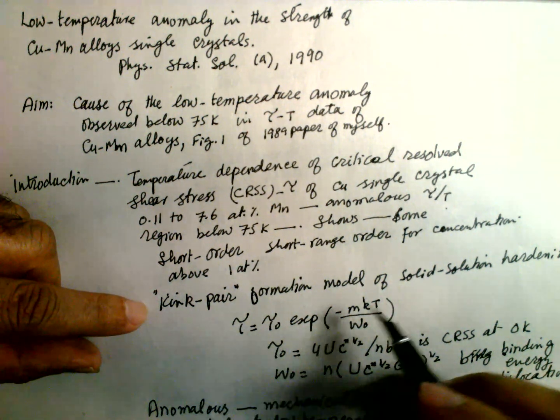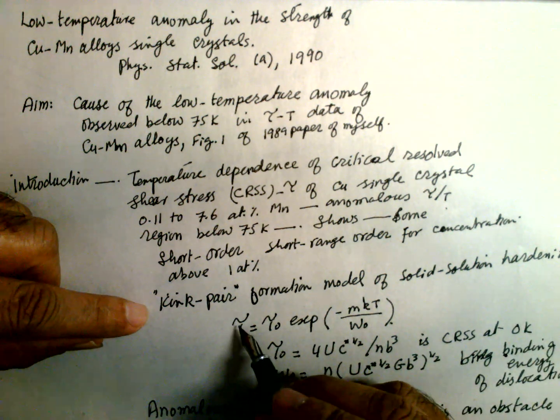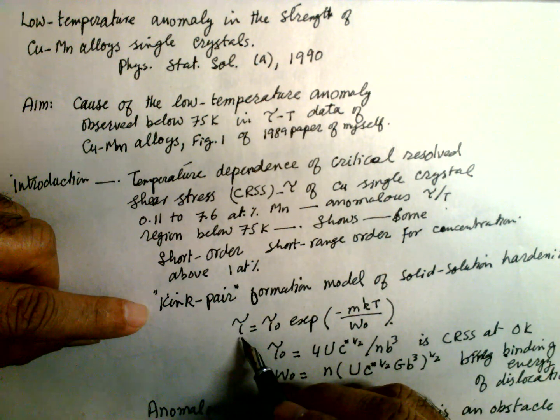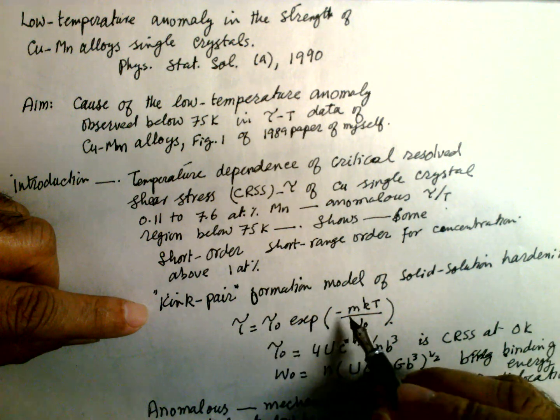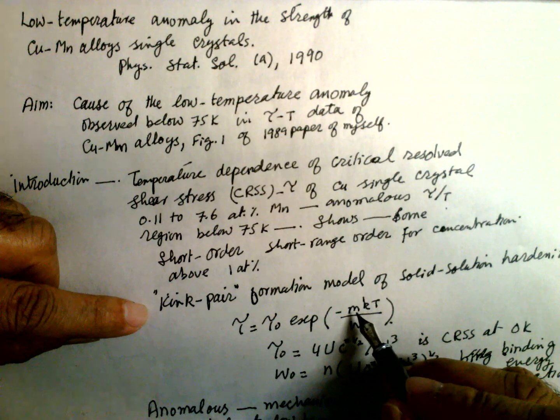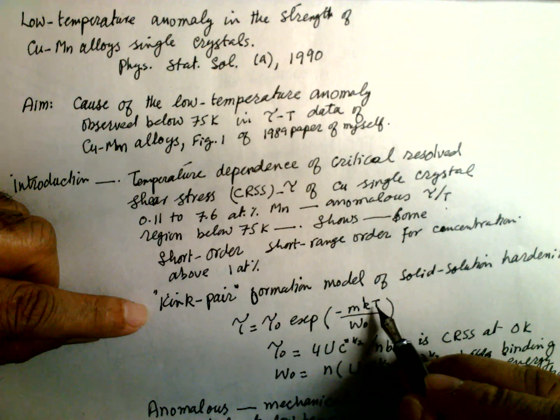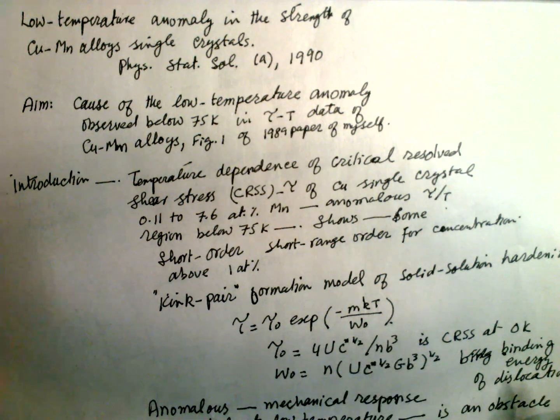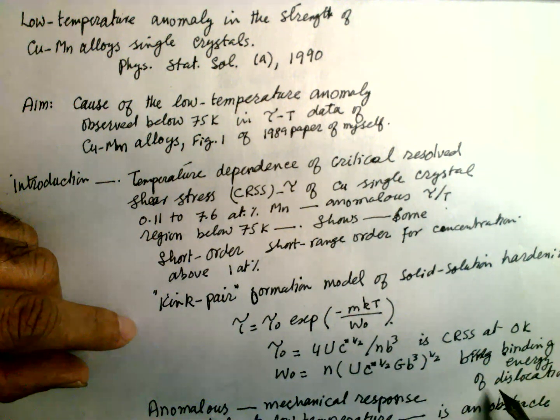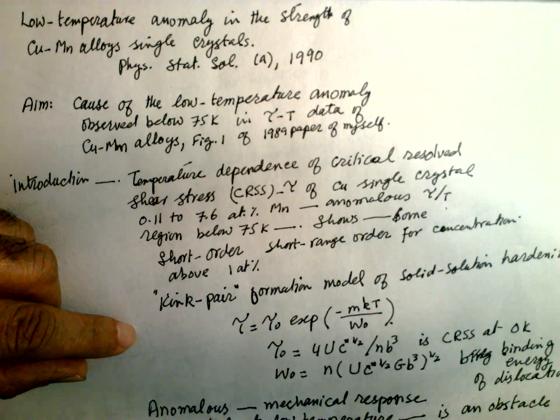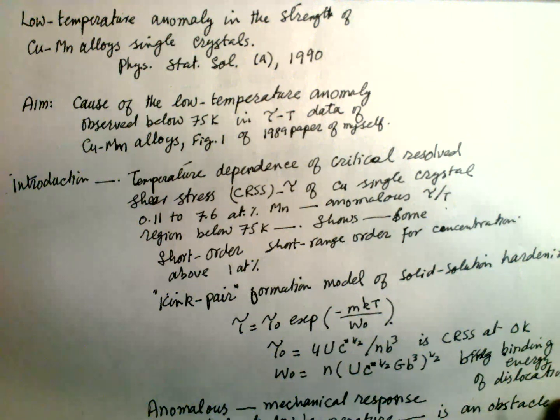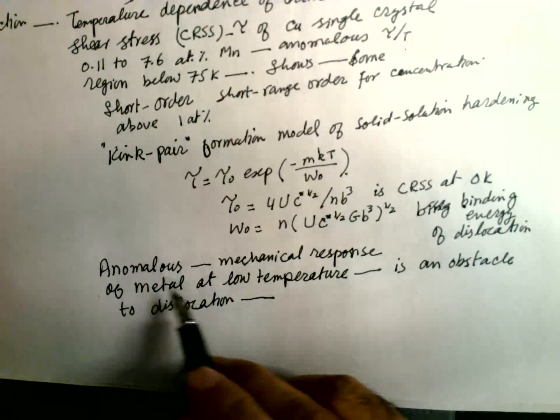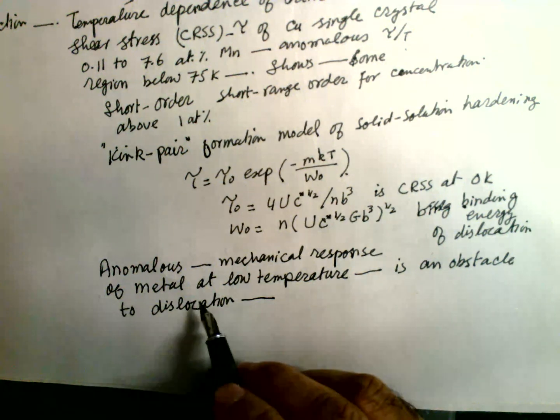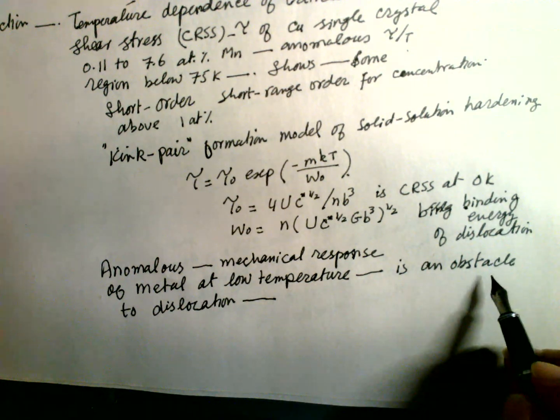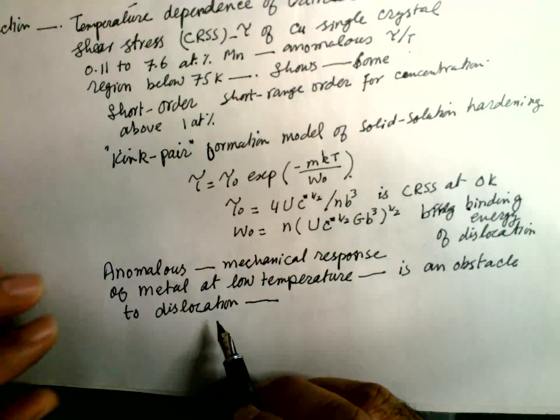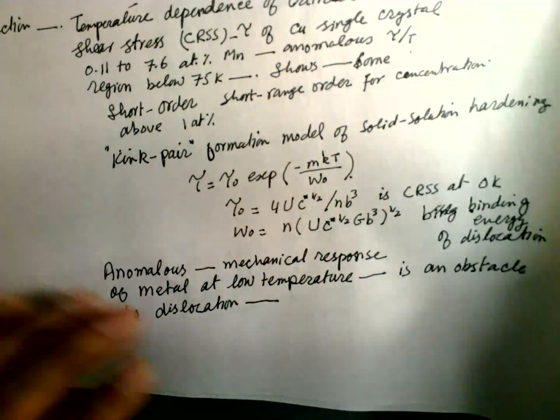The King pair formation model of solid solution hardening, where tau, the critical resolved shear stress, is equal to tau naught exponential of minus mkT over w naught. M is the mass, k is the Boltzmann constant, T is temperature in Kelvin, and w is the work function, which is the binding energy of the dislocation. Anomalous mechanism: the response of the metal at low temperature is an obstacle to the dislocation. We are using the metal model in the alloys.